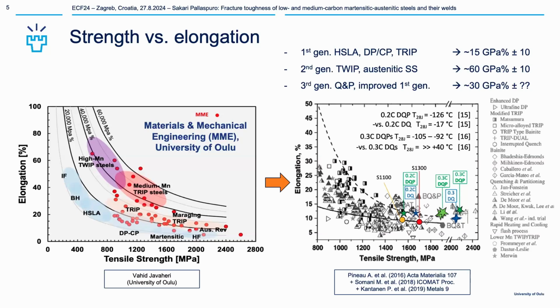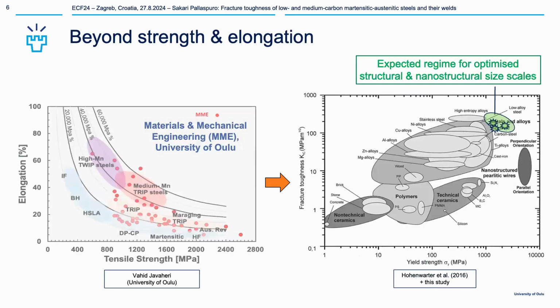Today we are talking about Martensitic Austenitic advanced high-strength steels, with yield strength and tensile strength starting from 1,000 megapascals and above. What is important here is that if you don't do wonders, they will drop in tensile elongation. Here are also some of the results we have put on a map. But of course, the session is on structural integrity, so we need to look further. Applying this method, when we iterate the processing correctly for these really high-strength steels, we can expect to extend the range of toughness properties as a function of yield strength when we have optimized microstructures for these materials.